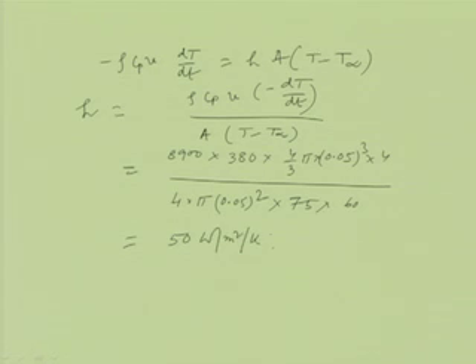into the cooling rate, 4 by 60, will come. Then the area is again 4 pi into r square, 0.005 whole square, into 75, the T minus T infinity is 75. This 60 will come because of the conversion of degree centigrade per minute to degree centigrade per second. So this value comes to be around 50 watt per meter square per Kelvin.